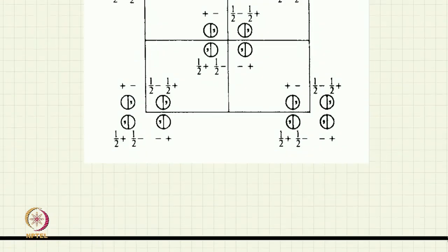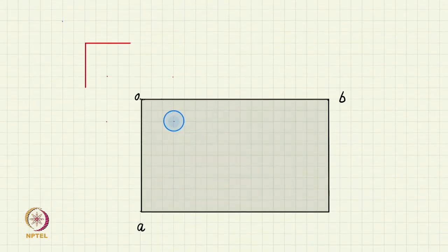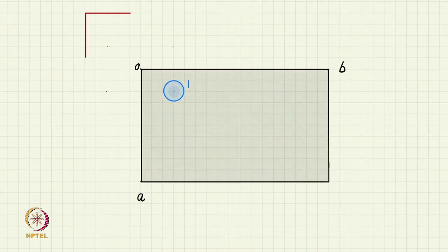Plus here actually stands for plus z, which means its z coordinate is some arbitrary value of z, but it is above the xy plane, above the AB plane, and its height above the AB plane is z. But to keep the diagram simple, z is not required and only the plus sign is given, which means that it has some height above the xy plane.